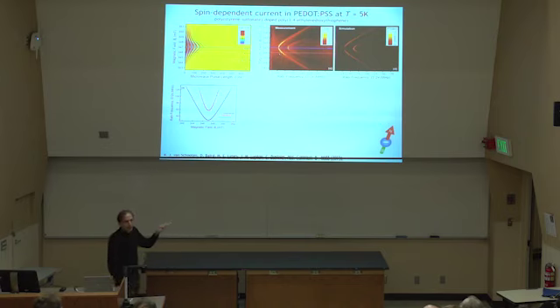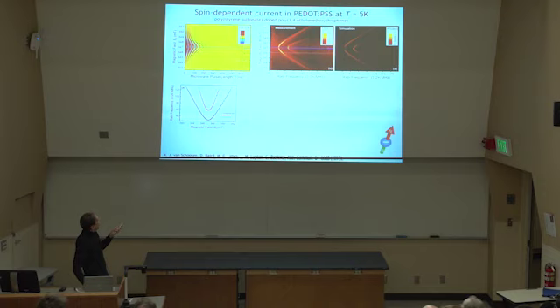So it's fair to conclude from just this crude comparison that these are weakly spin-spin coupled pairs that we see here. But if you compare now the Rabi frequencies for these different magnetic field conditions and the applied frequency that is calculated from those that are measured, that brings us to the plot that is given here. And you look at again the beat component, then you see again great overlap between data and the calculations, except you need to look closer. There's a slight deviation here on resonance, where it's not exactly the same.